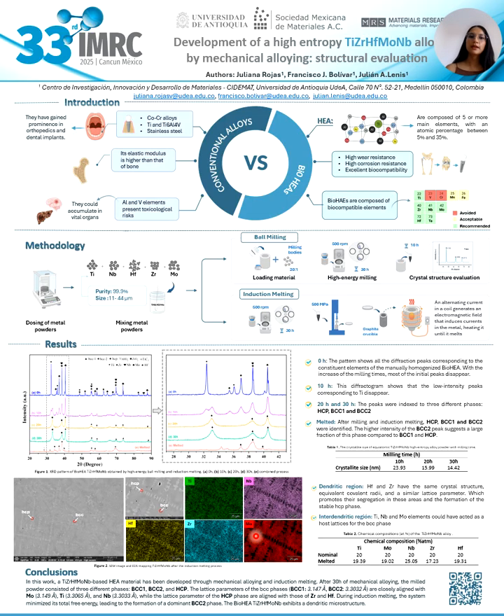During induction melting, the system minimizes its total free energy, leading to the formation of a dominant BCC2 phase, and the high entropy alloy exhibits a dendritic microstructure. Thanks for your attention.